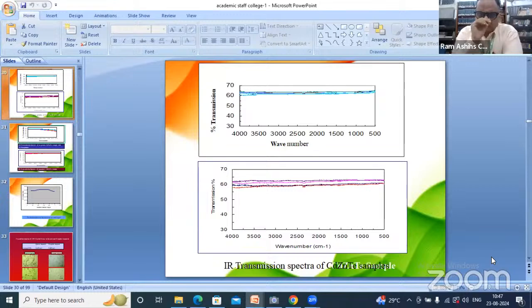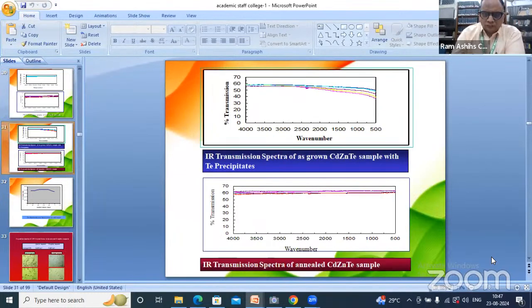This is the transmission, because this is used in backside illuminated devices. The transmission requirement is 60%. So our substrates are qualified for this transmission requirement. If the substrate transmission is degraded, then after annealing, we correct this transmission.